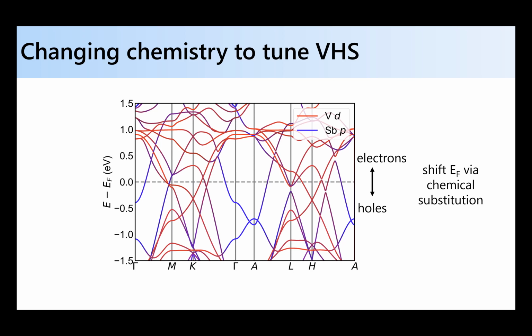What is it about this material that makes the properties so rich? Well, confusing. Yes. It's very confusing, yeah. I'm just gonna confuse you more because it's even weirder. I think a large component has to do with the fact that you have multiple Van Hove points here near the Fermi level. And which one happens to be dominant at a given temperature is probably driving the physics, but also I think there's an interplay with this antimony pz pocket that's rather unaccounted for in a lot of theoretical models that seems to play a large role.